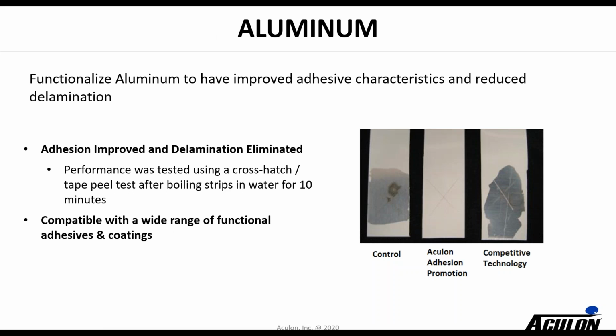So again, on aluminum, there's a lot of aluminum that's used for parts out there. A lot of it needs to be coated to protect the aluminum, and we're able to improve a lot of those coatings' adhesion to the aluminum surface. And you can see once again another crosshatch tape peel result, which shows very nice results.